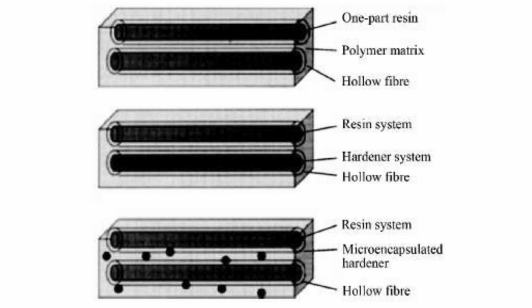Quantitative bending experiments demonstrated that this repair adhesive was also capable of hindering crack expansion. In accordance with this theory, researchers have constructed hollow tubes to meet specific requirements and employed various repair agents to facilitate healing. In short, the hollow fiber self-healing system is suitable for large-scale repairs and can be triggered multiple times, while the microcapsule self-healing system is ideal for rapid localized repair of micro-damage. The two can be combined to achieve multi-scale collaborative self-healing.